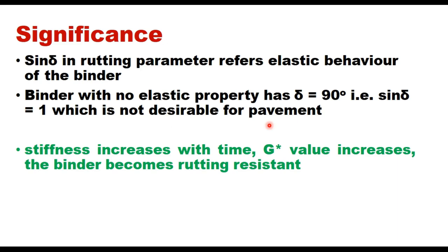We need some flexibility. Stiffness increases with time and therefore G* value will also increase with time. Stiffness increases with time because of oxidation and hardening of the binder, and that will increase the G* value also. The binder becomes very prone to cracking.